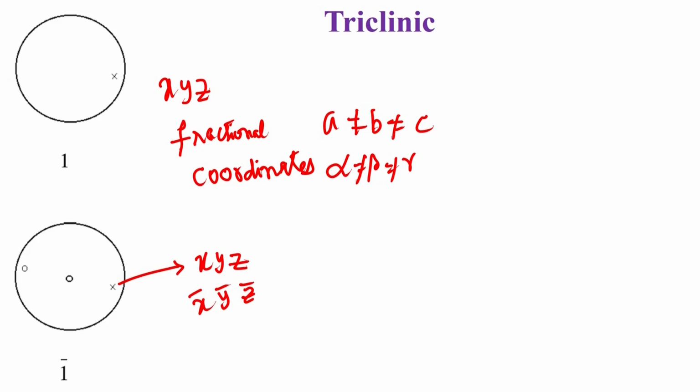in the case of the point group symmetry. We can also put in another piece of information on this slide, and that is the information about the Bravais lattice. We have already seen the 14 Bravais lattices in an earlier class. In the case of triclinic systems, because there are no rotation axes and no plane of symmetry and so on, no other possibility is there except a primitive system.